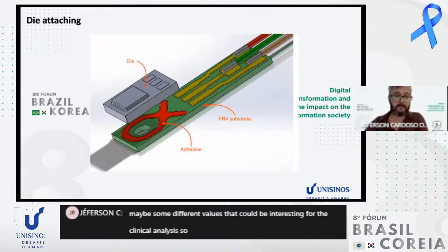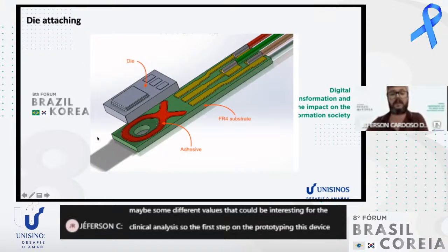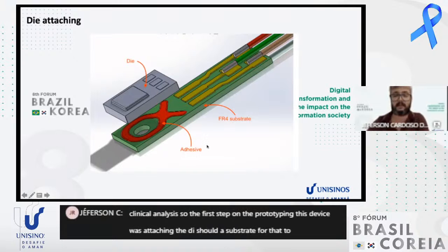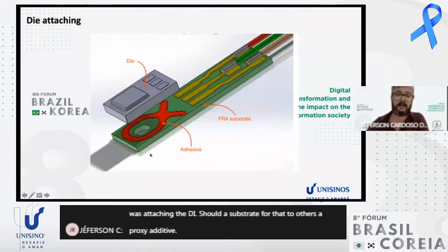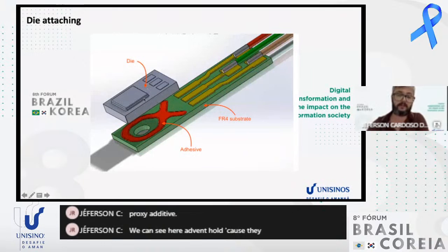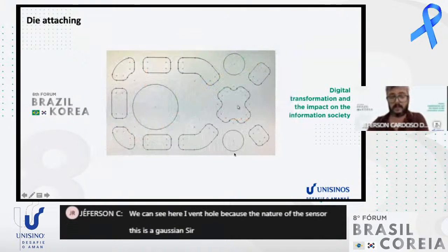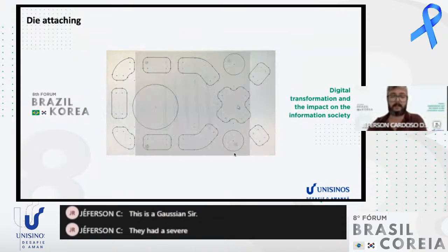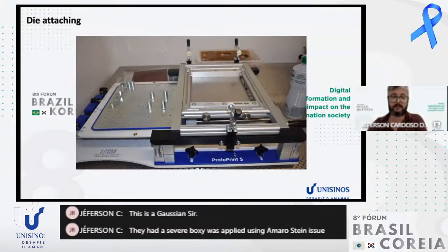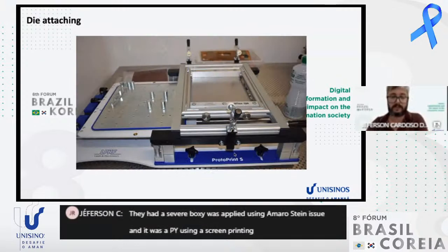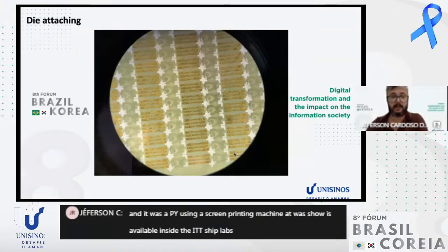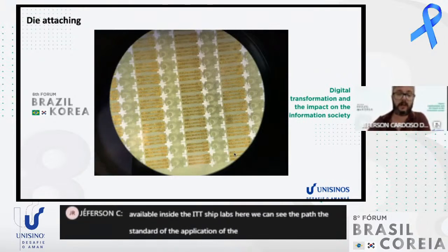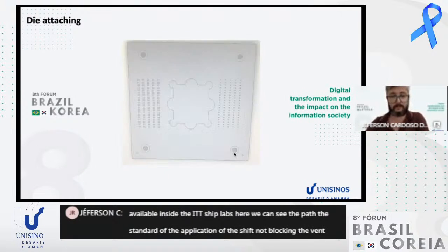So the first step in prototyping this device was attaching the die to the substrate. For that, we used an epoxy adhesive. We can see here a vent hole because of the nature of the sensor, this is a gauge sensor. The epoxy adhesive was applied using a metal stencil and a screen printing machine available inside the ITT Chip labs. Here we can see the pattern of the adhesive application, not blocking the vent hole.